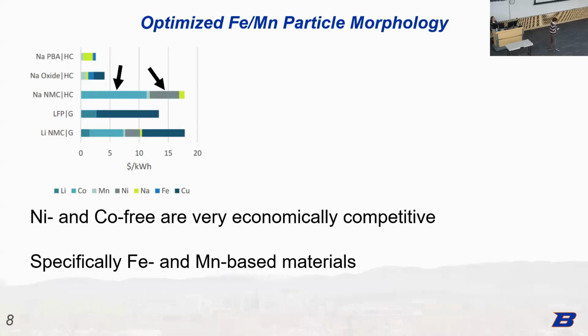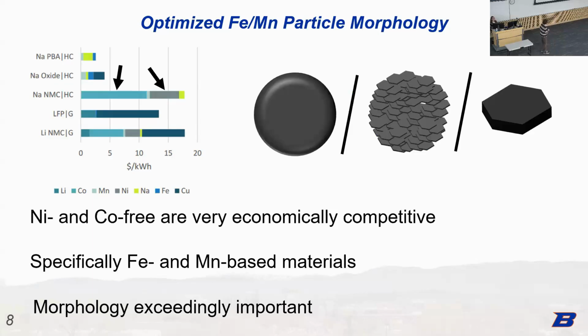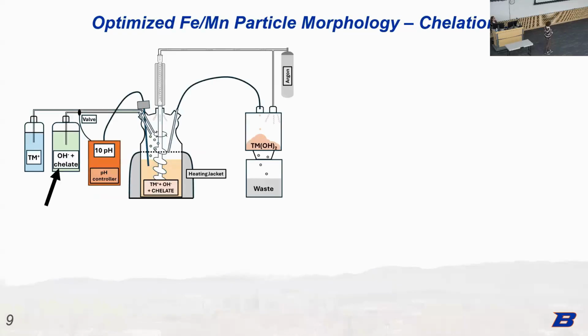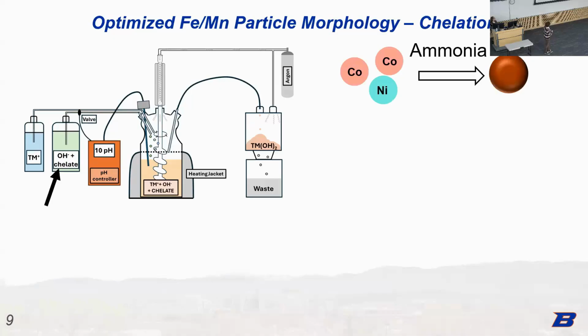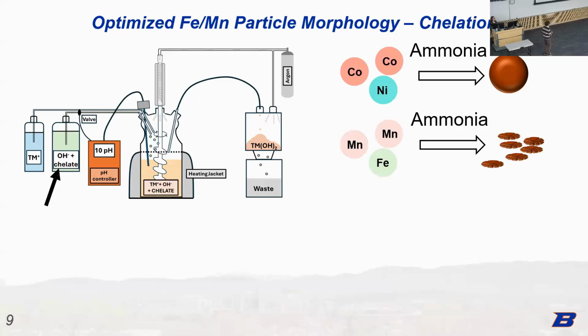How about that? And what you also want to do is when you make these materials, you want them to have a very good surface morphology. If you have a very high surface area enabled by a very small amount of particles, you will have a very reactive surface that then forms that interface that we do not like. So with contemporary lithium-ion production, what they use is a hydroxide coprecipitation reaction where you have effectively cobalt and nickel reacting with hydroxide. And then if you chelate it with ammonia, you can get these particles that grow into these beautiful spheres. However, if you replace nickel and cobalt with iron and manganese, they break into these very small particles that are uneven, flakily, and not optimized. Now, why is that?